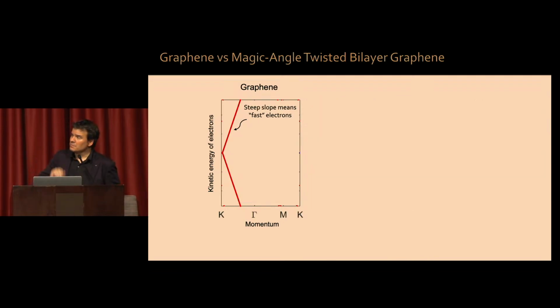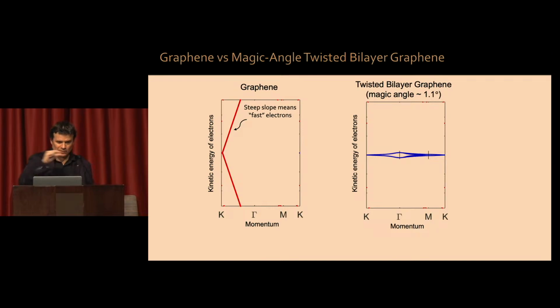Now, if you take magic angle twisted bilayer graphene, which means you take 2 sheets of graphene and you place them on top of each other, rotated with a precise angle of 1.1 degree. 0.9 doesn't work, and 1.3 doesn't work. 1.1 plus minus 0.1, give or take. Then what happens is that the kinetic energy of the electrons versus momentum looks like this. Looks very flat. It has a very small slope, which means your electrons propagate very slowly through this structure. And this we get just by rotating that 1 degree. We say that this is a flat band, for those who are a bit experts in the audience.